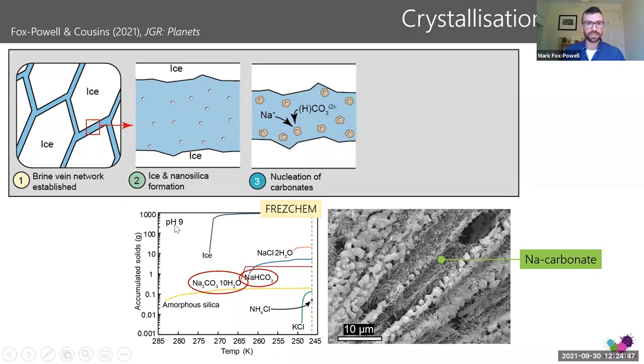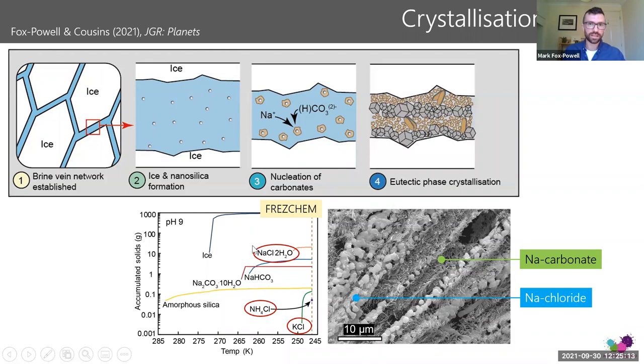And as we move to colder temperatures, we precipitate carbonate minerals. These are the next phases to form. And these are identified analytically using X-ray spectroscopy to be these small crystals labeled here. And again, due to the textures we observed, we interpreted these to be free-floating as a slurry in the brine veins at this point. And it's not until later in the sequence, where we have chlorides forming near the eutectic point, that these push through that crystal slurry and aggregate everything into the textures we observe. And these eutectic crystallization textures are also observed in metallic systems and also in igneous systems.